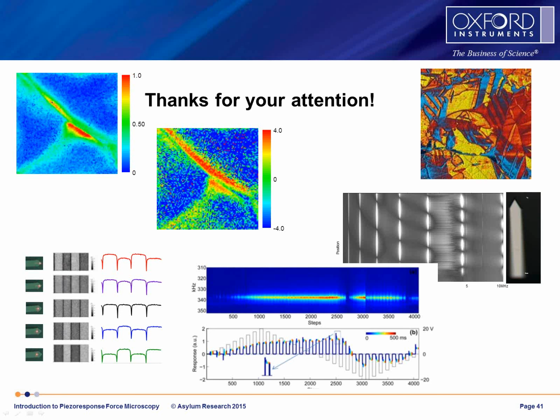Sergei, this first question I will give to you. In the case of both ion movements and ferroelectricity, where both contribute to the electromechanical response, is there a way to separate the responses that are coming from these two very different mechanisms? So it is a very complicated and very interesting question. In the purely ideal case, when we have the ferroelectric and the ionic material with the blocking electrodes, the answer is actually no, because the microscope detects either physical or electrochemical dipoles.